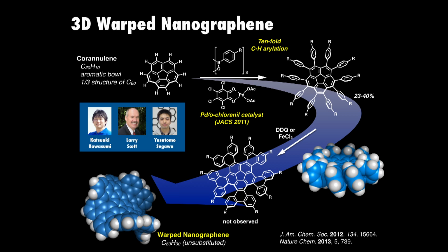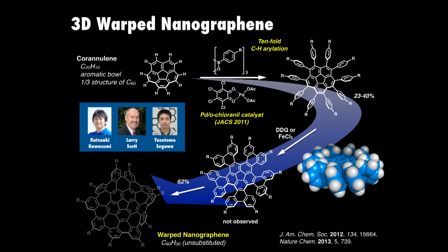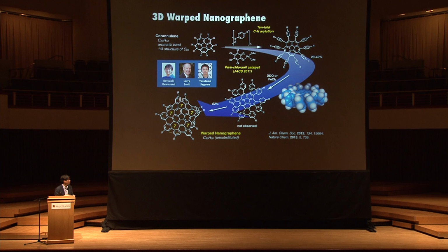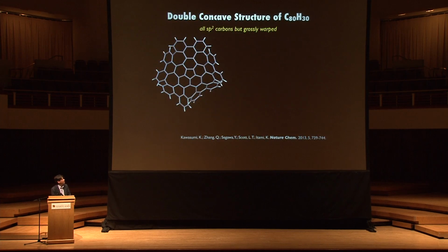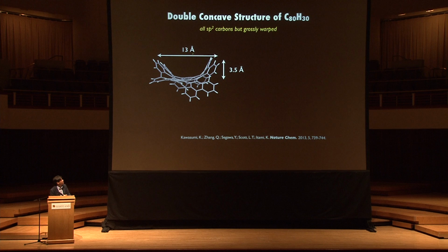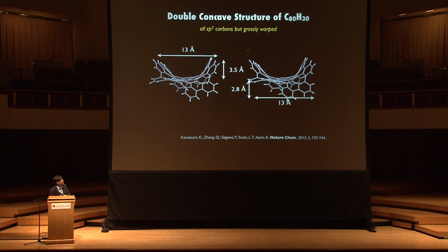He did that, but even below room temperature, he didn't observe this. Instead he found an over-oxidation product, right here. He found that he's forming 5 additional 7-member rings right here. This was very surprising because a 7-member ring cannot be planar, and this is all sp2 hybridized carbon that wants to be planar. This is a structure that he confirmed by X-ray crystal structure analysis. And this is all sp2 carbon, but you can see here, this is grossly warped, as shown here.